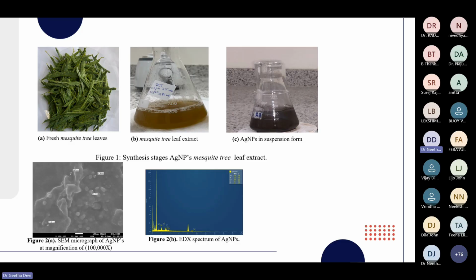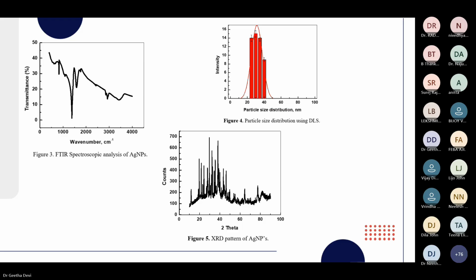This is the image of the synthesis steps, that is fresh mesquite tree leaves, which are converted into the extract, and that extract was mixed with the silver nitrate solution, and the synthesized nanoparticles were subjected to surface morphology study using scanning electron microscopy, and this shows the energy dispersive X-ray analysis. And also the characterization was done using FTIR spectroscopy, and the particle size ranges from 20 to 40, and the XRD pattern shows it is crystalline in nature.